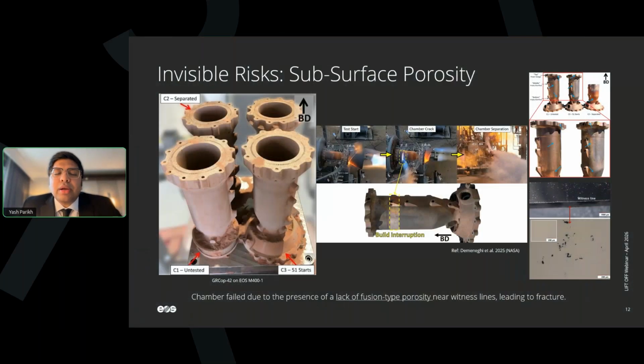You see, this was printed on our EOS M400-1. Four cylinders were printed in the configuration that you see on the left-hand side of the screen, and this was printed in GRCop-42. As I was telling you, they wanted to see the thermal mismatch. Again, in the laser powder bed fusion process, the solidification rate is 10^4 to 10^6 kelvins per second. They stopped the process in between and then restarted it. What came out is the build interruption and the witness line formation on the extreme right. Right below, you see a witness line, which has lack of fusion porosity. That was the key reason for the failed part during testing, which you can see on the middle screen, how it progressed. So go to the next one, please.